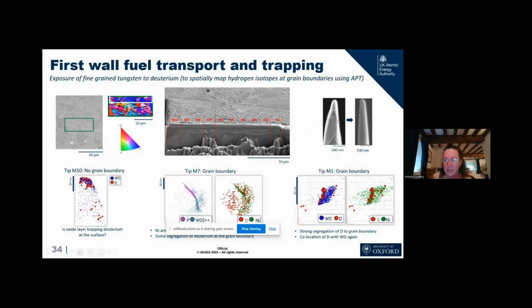And we're looking at those tiny needles on atom probe tomography, and we're picking up from the segregation of things like the phosphorus and the nickel, where the grain boundaries are, and we're looking to see if our deuterium is trapped along the grain boundaries and whether it's associated with some of the tungsten oxide phases. So we're beginning to pull not only the impact of the microstructure on damage resilience, but also the impact of the microstructure on the tritium trapping. And you recall a couple of minutes ago, I said to you, tritium, transmutation, and displacement. So lots of new work coming out at the moment.